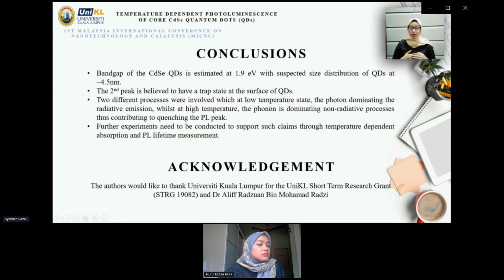We also found that the exciton longitudinal optical, ELO, value is 25.6 milli-electron volts, which is similar to that reported by others. This study gives us a highlight of the exchange process, radiative and non-radiative emission processes, which may contribute to more future experiments.